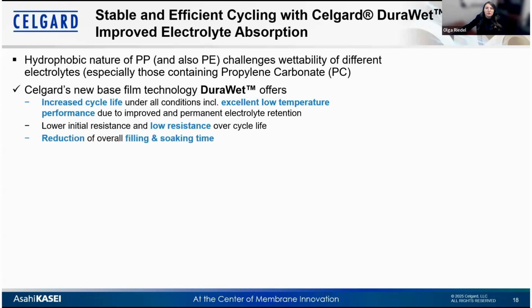DuraWet can also reduce, therefore, overall filling times and also reduce soaking times, and therefore improve yields, so as you are not running into copper dissolution, especially if you're not using a pre-charging step.